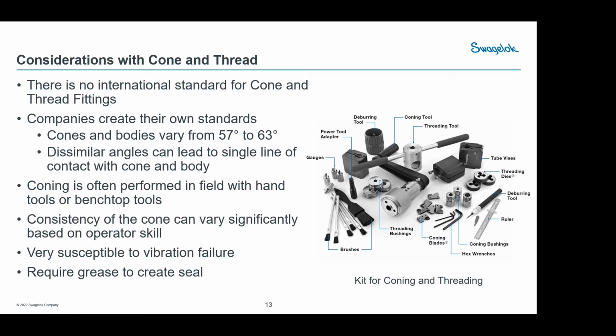If you have a small angle in your body and a big angle on your tube, what'll happen is they could just seal right on the corner and not actually slide. Vice versa, if the angle's very steep on the tube and the body's got a very big chamfer on it, when that tube goes in, it can actually bite in and give you what's called a coined surface down below, and actually put an indentation into the fitting. That's fine for one makeup, but unfortunately, if you try to remake it, you've got to make sure that that coin surface always matches back into the coin. That doesn't work very well.